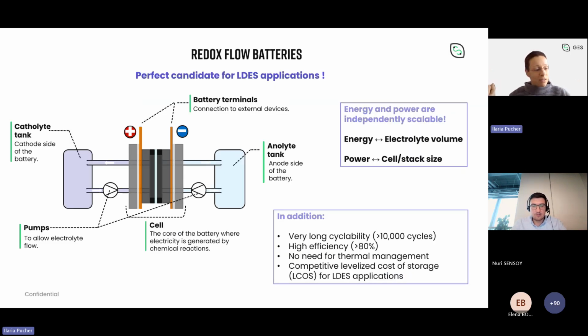So what are redox flow batteries? The redox flow batteries are batteries in which energy and power are decoupled. And therefore they are independently scalable. So in particular, energy is defined by the volume of the usually liquid electrolytes in which redox couples are dissolved, while the power is defined by the cell area or the stack size where actually redox reactions occur. In addition, redox flow batteries usually have a very long cyclability, usually more than 10,000 cycles. They do have a pretty good energy efficiency, more than 80%, and they don't usually need thermal management.